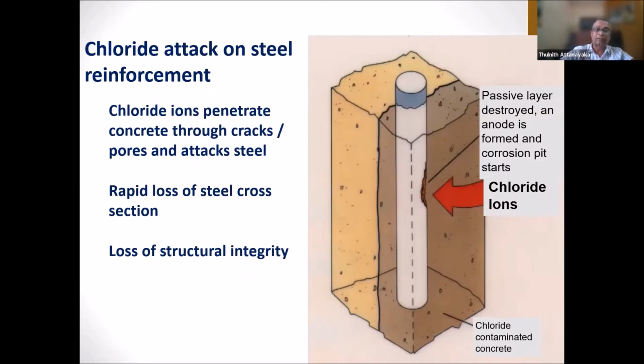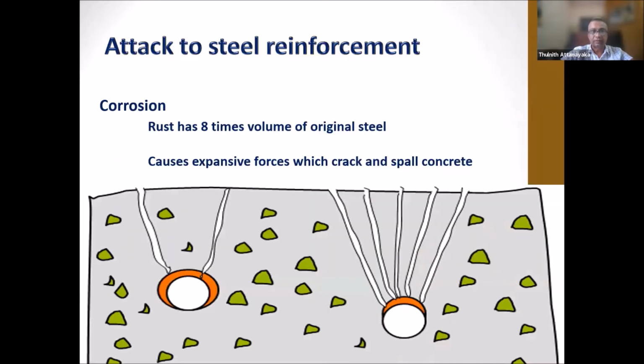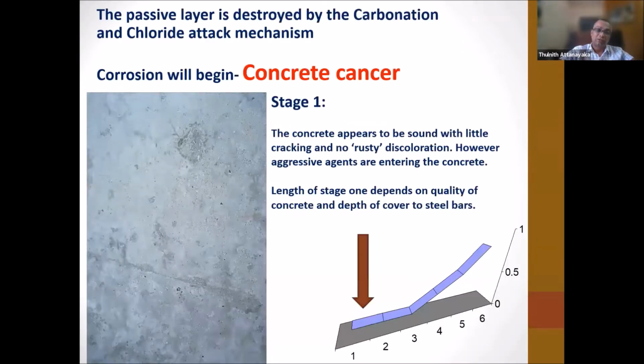Again, the chloride penetrates concrete through the cracks and pores and attacks steel. It will give rapid loss of steel, not like carbonation. It will introduce corrosion pits. That is loss of structural integrity. Once the corrosion has started in the concrete, you can see the rust has 8 times the volume of the original steel. That's why the corroded reinforcement inside the concrete causes expansive forces, which crack and create spalling of the concrete. So we would say that is the concrete cancer.